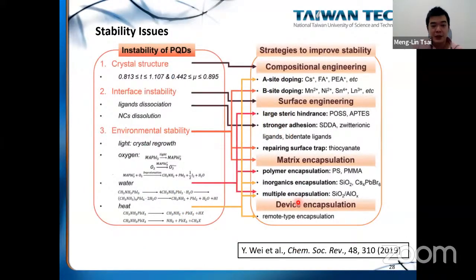So these are the stability problems. The instability can come from the crystal structure and from interfacial instability. Usually for quantum dots we need a ligand at the edge of the quantum dot to encapsulate it and prevent it from growing larger. But if the interaction between the ligand and the crystal is too large, then your material will dissolve. If the interaction between the ligand and your crystal is too small, then it will not be able to protect it from solvents or neighboring crystals, and it will not effectively prevent it from growing bigger.